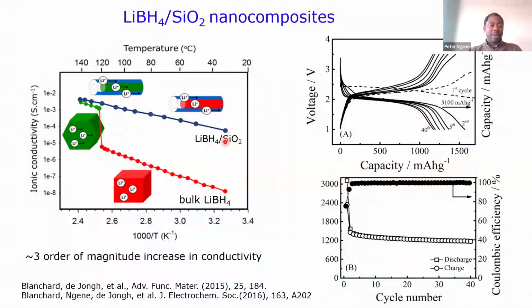So this actually works. We do know that at the interface, we have very fast moving lithium ions, and far from the interface you have lithium ions that don't move as fast as the other ones. So if you're able to reduce this dimension, the pore size of the silica scaffold, you can fill it completely with a very fast moving electrolyte where you have very high conductivity of lithium.